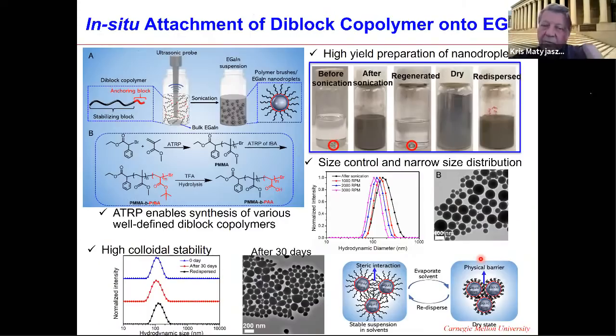You can make them by grafting from, but you can make them also by grafting onto. This is an example of a block copolymer, something similar to what Craig was showing, based on t-butyl acrylate. After hydrolysis, we get acrylic acid, which can attach to the surface, and then they can be dispersed and stable even after 30 days. They can be separated, redispersed again. And depending now on centrifugation, you can also fractionate their size and have it in a different way.